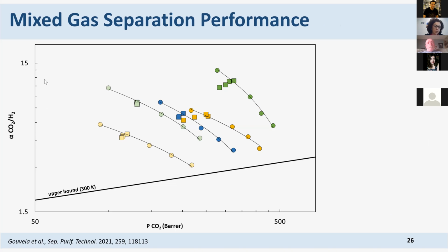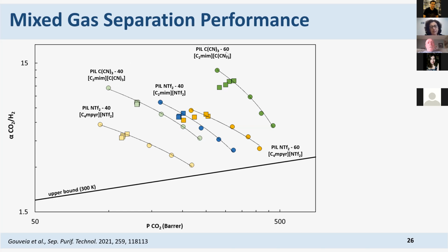So this is the Robeson plot that tells us the efficiency of my membranes. Here it plots the selectivity versus the permeability of the most permeable gas. The upper bound is the current state of the art, and so we want to surpass the upper bound to surpass the current state of the art. So here are the membranes that we did. Again, 40% of ionic liquid is less permeable than 60%, so 40% of ionic liquid is less efficient than 60% of ionic liquid. In terms of efficiency, this is a little bit smaller, but it has a much smaller CO2 permeability.